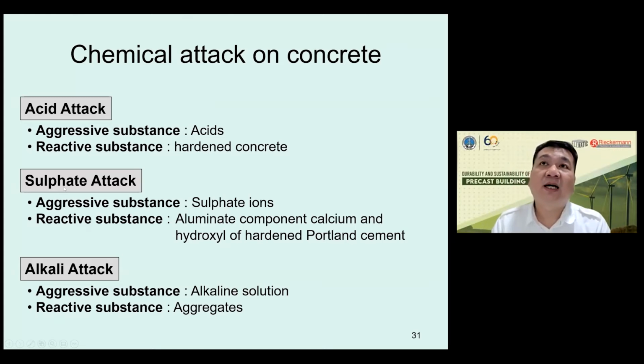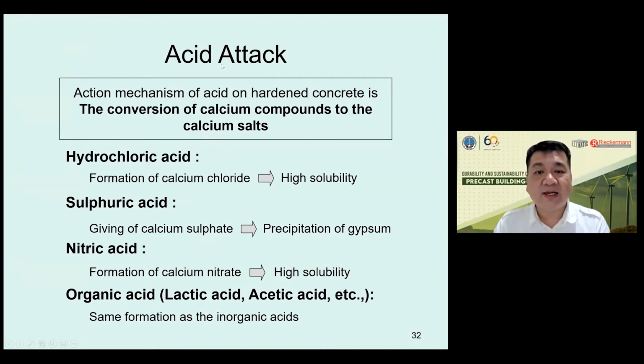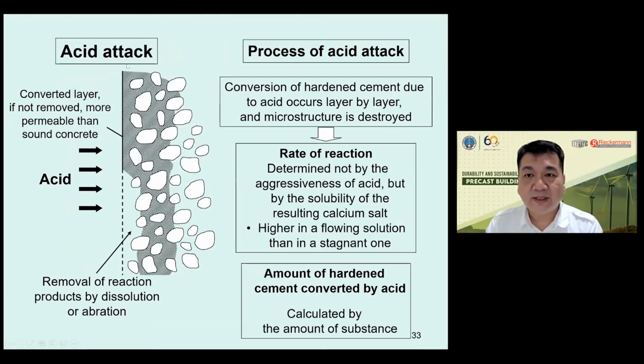Sulphate is material from the seawater, and some soil also has sulphate. So sulphate is material that attacks the aluminate component in the Portland cement. So aluminate reacts with sulphate. And then the other thing is alkali of the concrete reacting with the aggregate. So for the acid, we have lots of acids that we need to understand. There's hydrochloric acid, sulfuric acid, nitric acid, and organic acid. Normally, the building will face organic acid because we have oil spills and other types of acid. Cleaning solution acid is also part of this, and it will convert the calcium compound of the reacted cement into calcium salt. So this is the schematic.